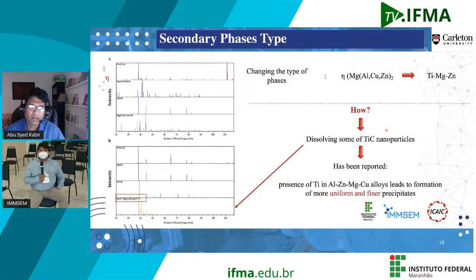Okay, so this is the hypothesis that we have: that the presence of titanium carbide nanoparticles actually changes the precipitation morphology. We found a trace amount of a very new type of composition that has titanium in it. So we are guessing this new composition of precipitates actually does not lead to the formation of continuous precipitates in the structure.